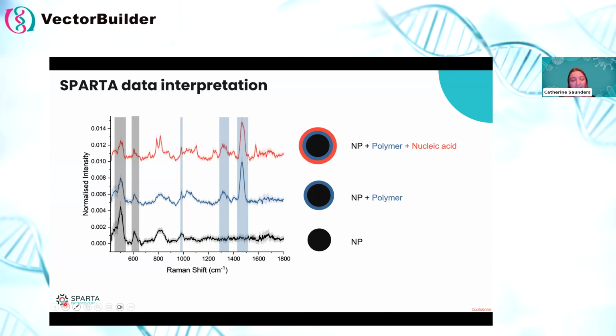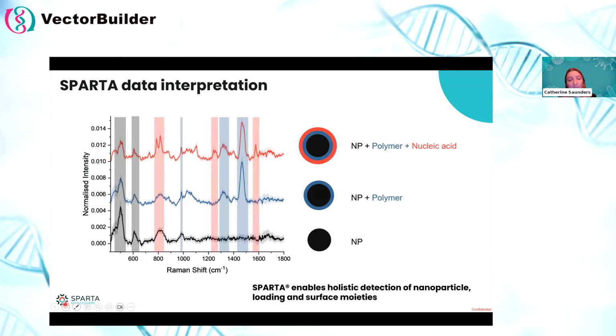What you'll see is, again, in this iterative way, if I take this system, so I take the nanoparticle plus the polymer plus the nucleic acid, we have these same peaks in the nanoparticle and the polymer, and we additionally have these peaks from the nucleic acid. So similarly, we can assign these to the nucleic acid specifically. Okay, so this is the average spectra.